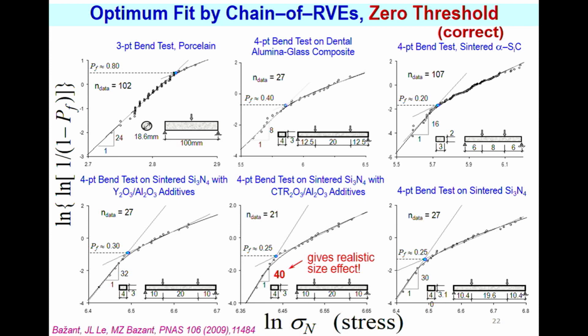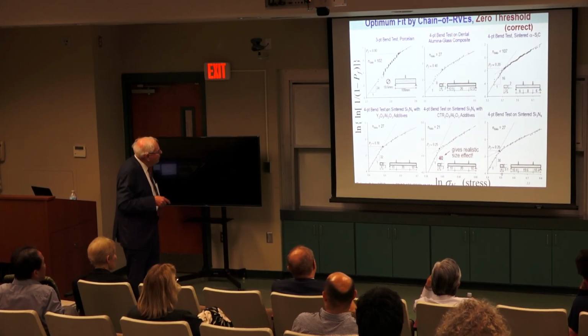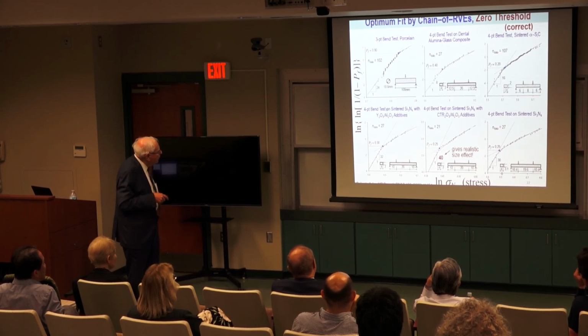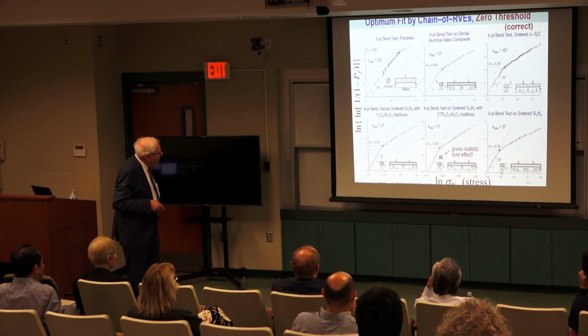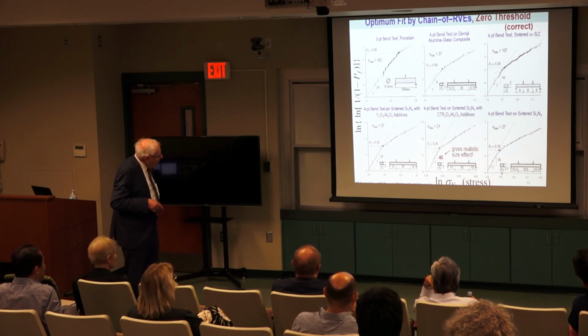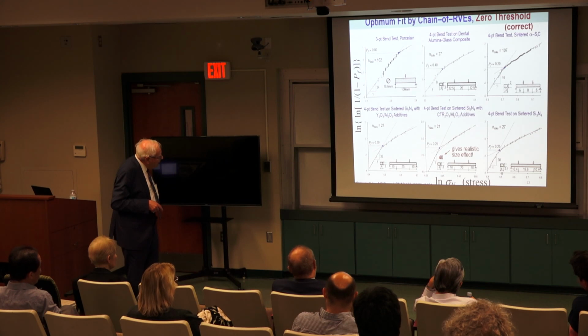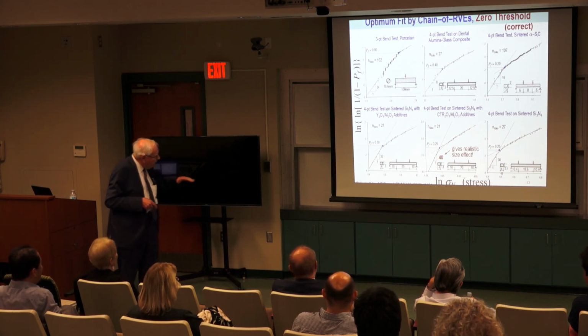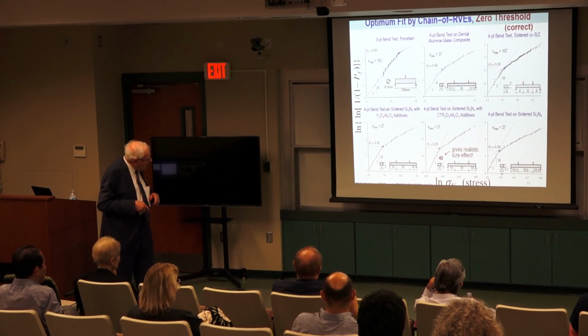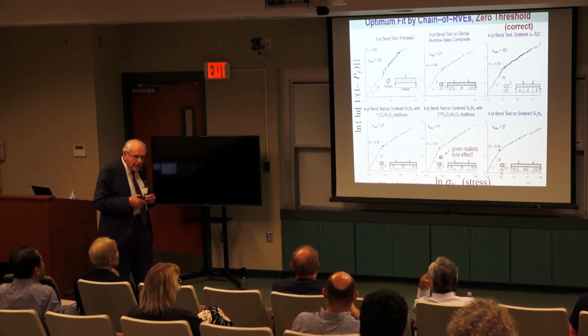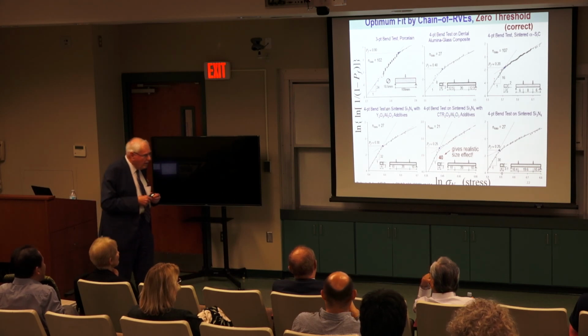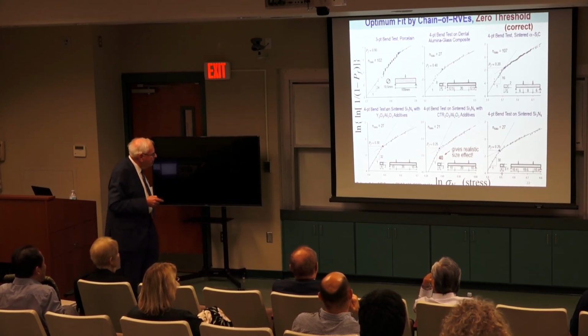Now these are some more recent papers on various ceramics, porcelain, dental composites, silicon carbide, silicon nitride, and so forth, taken from recent literature, and they all observe these deviations. If you plot it in Weibull scale and you plot the total stress, okay, you observe these curves. It is interesting to note that the exponents of the Weibull part are high, like 40. That size effect in the mean is actually 1 over this exponent. Size effect would be size exponent 1 over 40, very small. And indeed, size effect is very small in these materials.